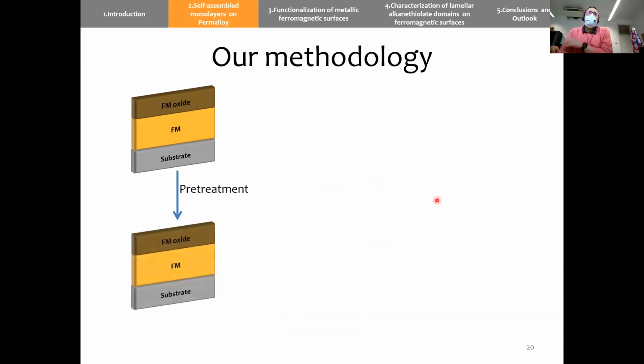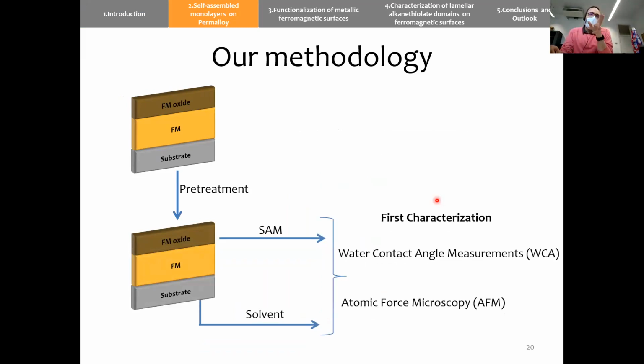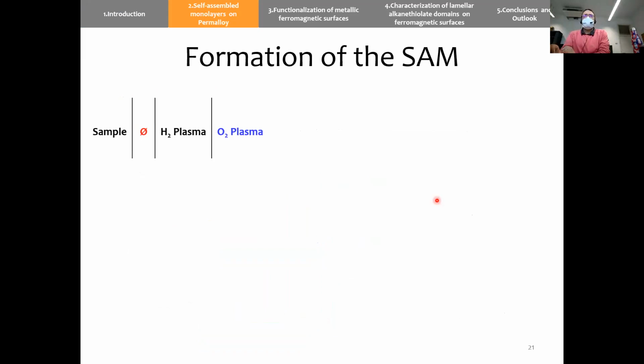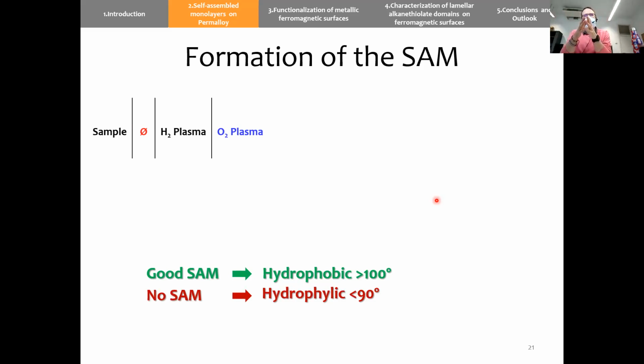And in our case, we first pretreated the sample, and then we had a reference, and then we measured the contact angle, because we know that this kind of SAM should be more hydrophobic than the substrate itself. And then we characterized the topography by AFM. So, just to remind you, this kind of SAM is very hydrophobic. If we observe a contact angle above 100 degrees, we know that we have a high quality SAM. If it is less than 90 degrees, it means that we have no SAM at all.